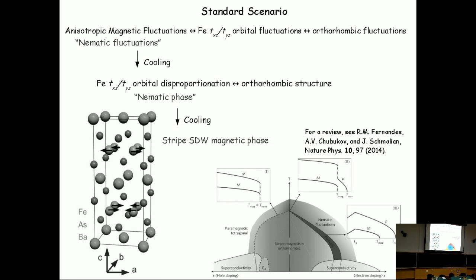And then a phase diagram was actually drawn. I hope you can see that here, where here you have the electron doping and here temperature, and at low doping and low temperature, you have basically the orthorhombic phase with stripe magnetism. And then for zero doping, you have this transition that is both a structural transition and a magnetic transition, where the system becomes tetragonal and non-magnetic.